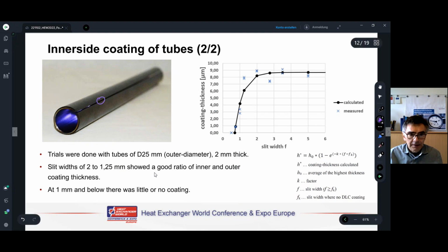You see here a very thin gap in comparison to the other measures. So you can imagine the final forming before welding is simply not very difficult. It's in the elastic range of the material. We have not really to form it, and it will be a tube in the roundness which is required. The area where we had satisfying results is in this range. With bigger gaps, it makes not really a sense in our meaning, so we should go as narrow as possible.